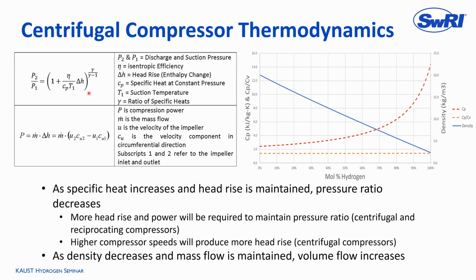The other thing to note, how do you do more work? Well, work is related to power. So we've got to look at mass flow times power as work. In a centrifugal compressor, there's another equation that we use to determine work, and that's related to the impeller rotating speeds. U is the tip speed of those impellers, and then C is actually the gas speed exiting the impeller or entering the impeller. And so that shows if you want to increase the work in a centrifugal compressor, you have to do that by increasing the tip speeds with the same number of stages. There's another option where you just add more stages running at the same speed, and that'll get you an increased work per stage. So that leads to some challenges in hydrogen compressors.